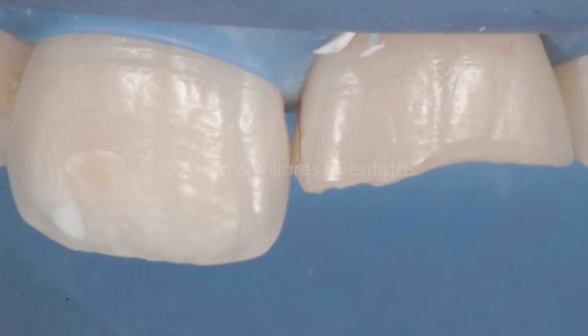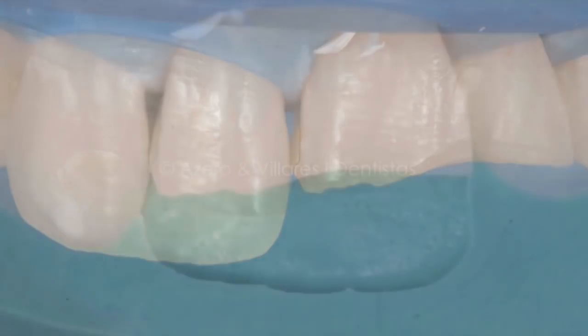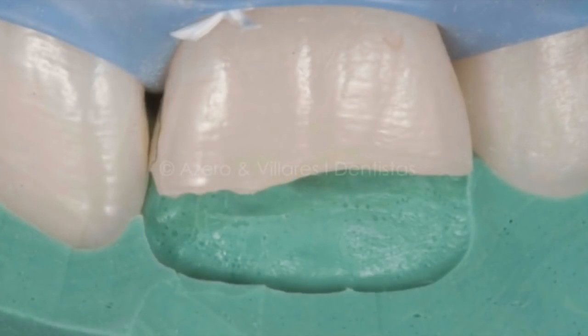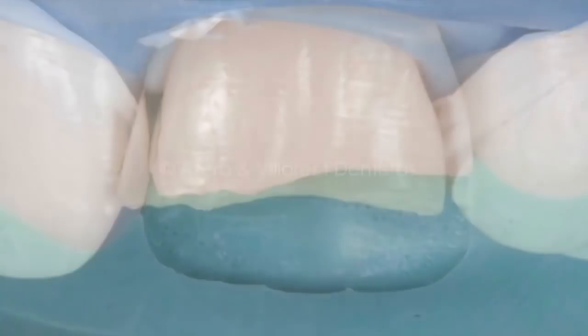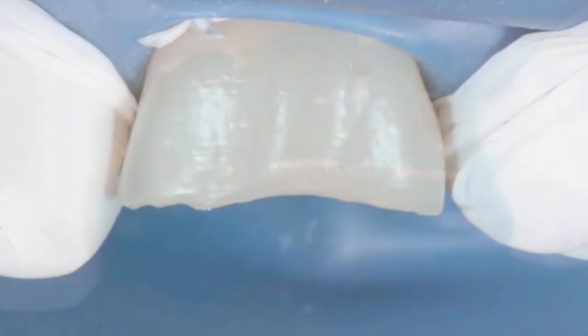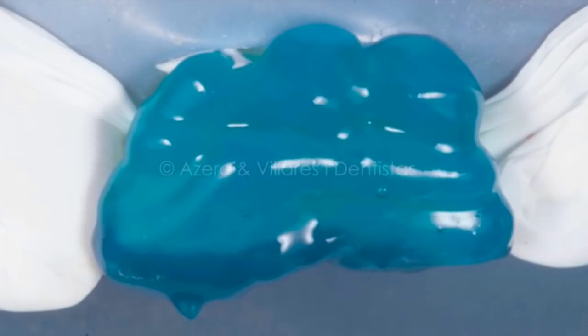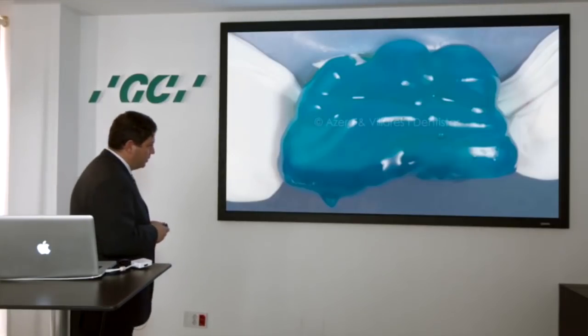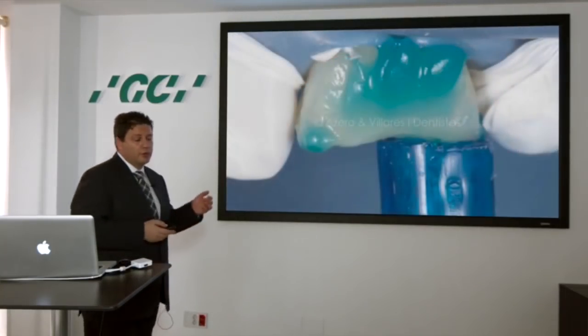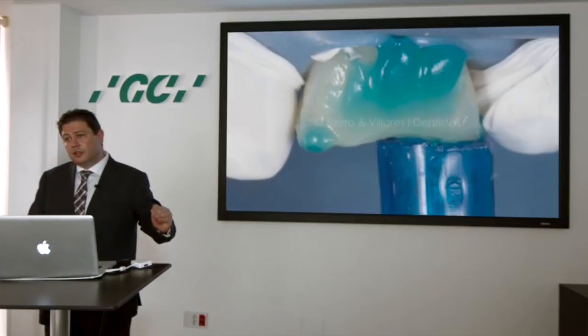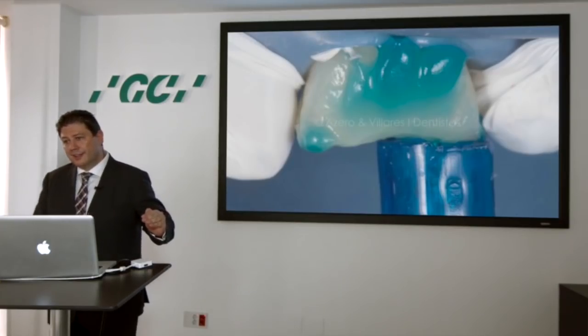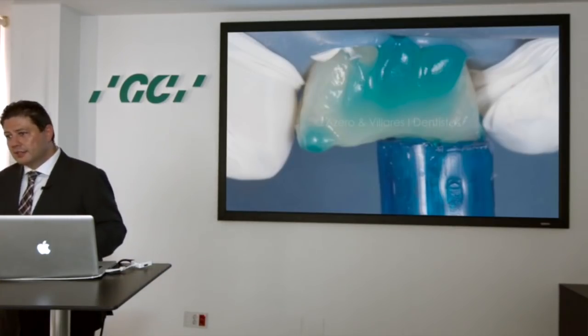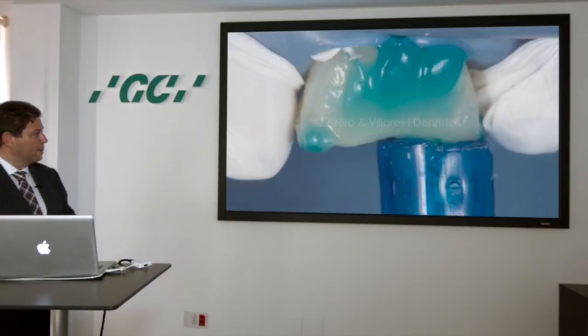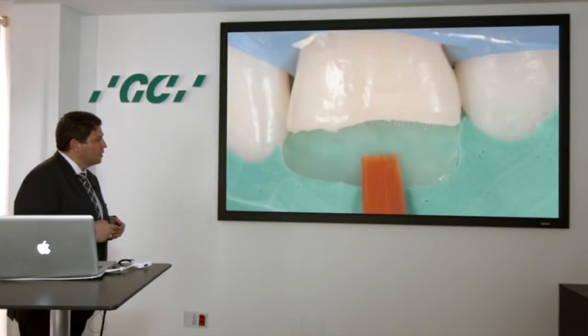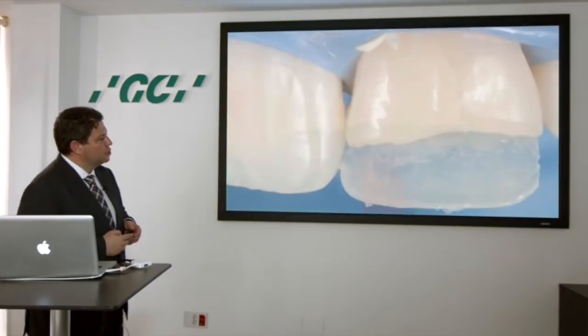After making the isolation with the rubber dam, what we do is check our silicone matrix and go through the adhesion process with the etching. Prior to that, we seal the entrance of the endodontic access with a glass ionomer. Then we apply the G-ænial Enamel.